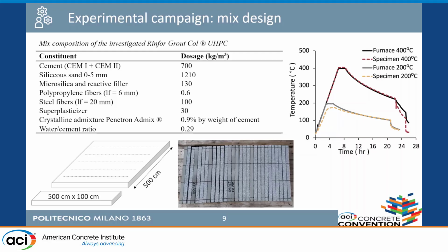The heating is very slow for the reason discussed before. Because we don't want to have thermal gradients inside the specimen, because we want to assess the material behavior and not the structural behavior, because with thermal gradients we also introduce stresses that depend on the geometry of the specimen. Then we maintain the temperature for 1 hour or 2 hours, I don't remember. And then we have a cooling that was very slow, less than 1 degree C per minute.